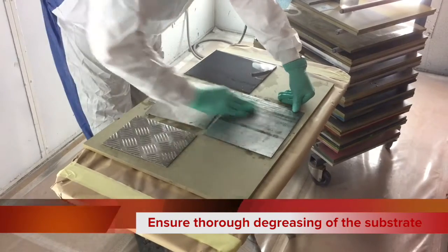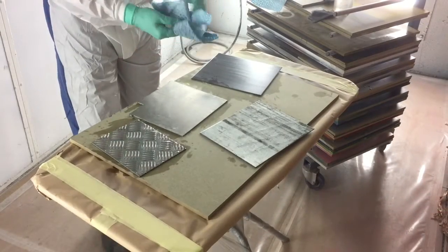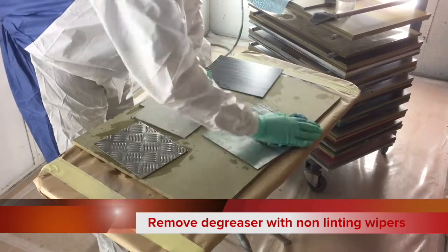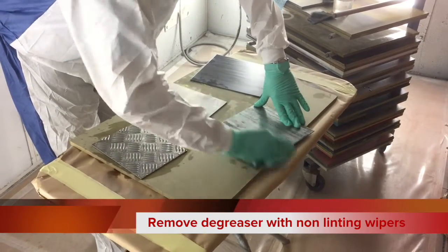The ready for use mixture may be applied onto a suitably cleaned and degreased or blasted substrate at a film thickness of up to 200 microns.